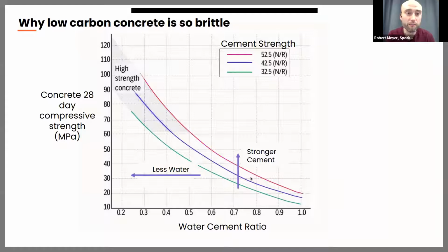But there's another level that most people don't know of, but which is even more powerful than just using better cement, and that is using less water. So for example, what you see on the x-axis here is the water-cement ratio. That means, for a water-cement ratio of 0.7, I take 7 liters of water per 10 kilograms of cement. And if I then take this rather weak cement, I get roughly 28 megapascal for